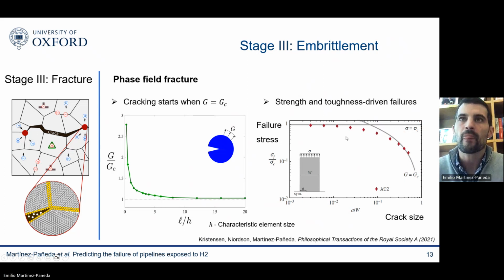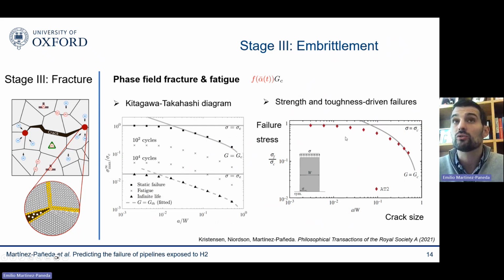strength of the material. And in fact, when you incorporate this, you can extend this model to fatigue. You can see here that we can define a fatigue degradation function that is basically a function that degrades your fracture energy with accumulating load history. And when you do that, you get these KT diagrams that are well known in fatigue. So as an output of the model, you can quantify those KT diagrams. You can calculate for both finite and infinite life. For as many cycles as you wish, you can determine these KT diagrams as an output of the model. So again, in very good agreement with well-established fracture and fatigue mechanics.